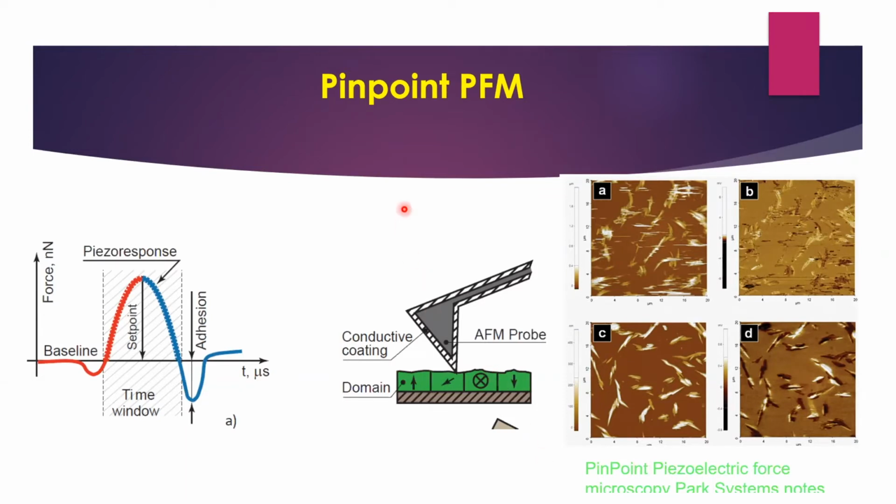And how does this pinpoint PFM work? Remember that when you measure this force curve, there is a time window where the tip is in contact with the sample. By using this time window of the contact, you can apply the AC bias that you need to measure the piezo response.